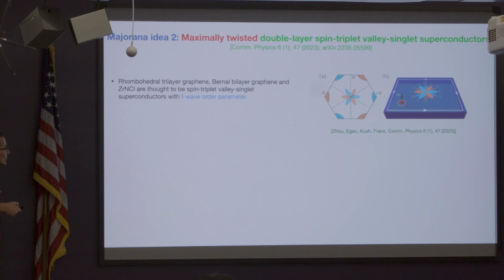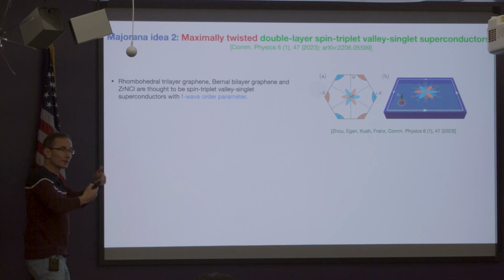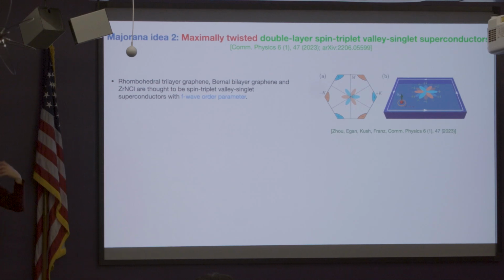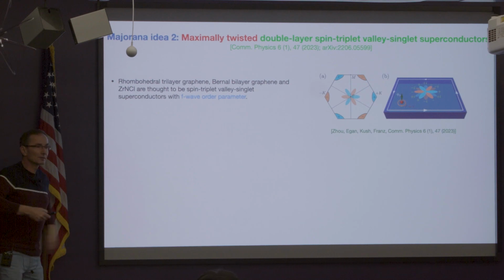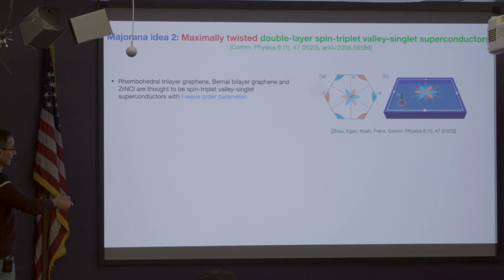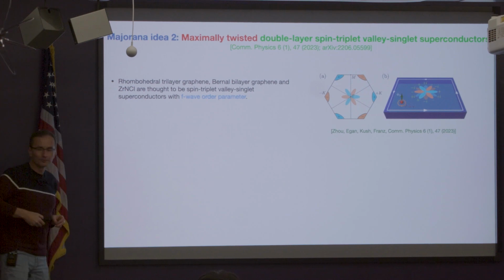You want something odd under inversion if you have only one type of spin, because you cannot create spin singlet. You only have spin triplet that's even under exchange. So in order to satisfy the Fermi statistics, you want something that is odd under spatial inversion, and that's why you need odd angular momentum here. Now, why F? Well, F-wave, because it's L equals 3, has precisely the property that fits nicely on this hexagonal Brillouin zone. Basically, what it does is that you simply have an order parameter that is positive here, negative here, positive here, negative here, and so on. Okay, so that's your F-wave with this type of Fermi surface.